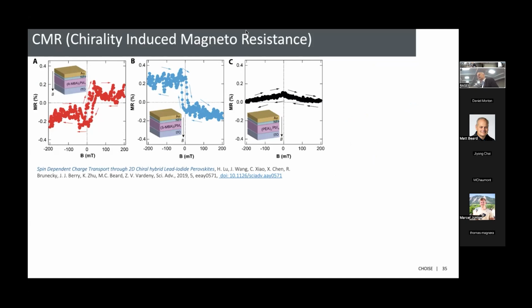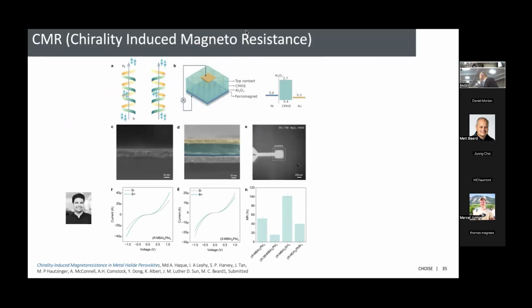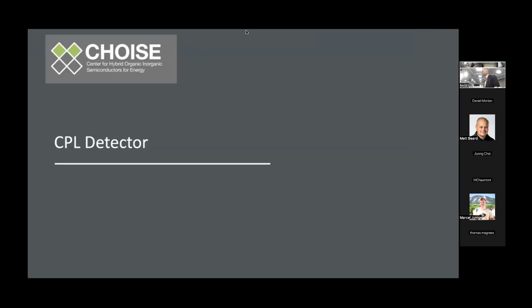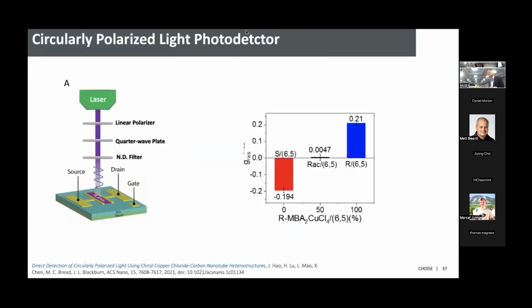So we published this paper. You can say, oh, well, your magnetoresistance is only 0.2%, but Azim here, he's done really well. And so now he can get this up to over 100%. Really impressive results, not yet published. Okay, what else can you do? You can do a CPL photodetector, and you can make this with Jeff Blackburn. You can make some sort of detector over here, make it chiral, it absorbs light, left-handed or right-handed. It'll have a higher response depending on the chirality. So you can detect whether your light source is polarized. So that's a CPL light detector.